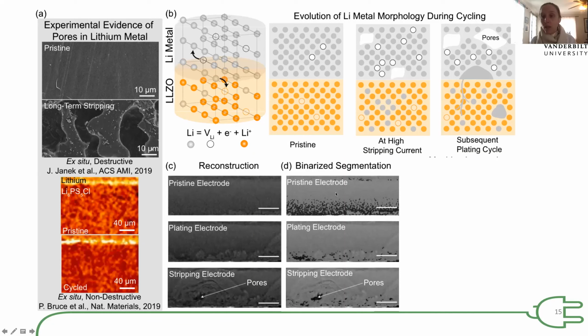If we wanted to analyze in three dimensions, we have to binarize our image, which basically is where the human in the loop, the human doing the analysis, picks an arbitrary pixel and says that attenuation at that grayscale means that I am a void or I am lithium metal. So we can discern the two phases. When I binarize the system, essentially all the stuff in gray is the lithium metal. All the stuff in black is presumably pores, or in this case, maybe non-uniform interface. However, there's a lot of variability from person to person and group to group on how you do this segmentation and binarization.